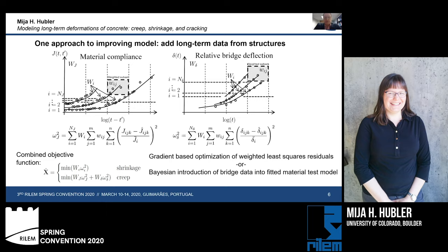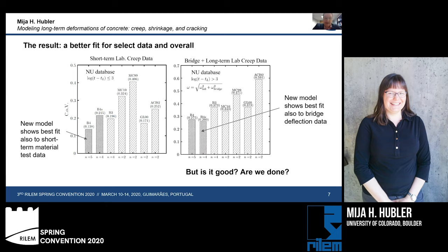Okay, so for optimization, we could use, for example, a gradient-based optimization of weighted least squares residuals, or we could use a Bayesian introduction of the bridge data into the already fitted material test model. What we found is that both approaches give approximately the same solution. Either way, we arrive at a better fit for both selected short-term data from the laboratory, as well as overall fit for the entire database of data that we have available.